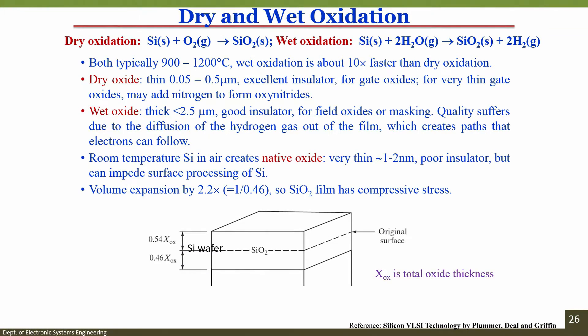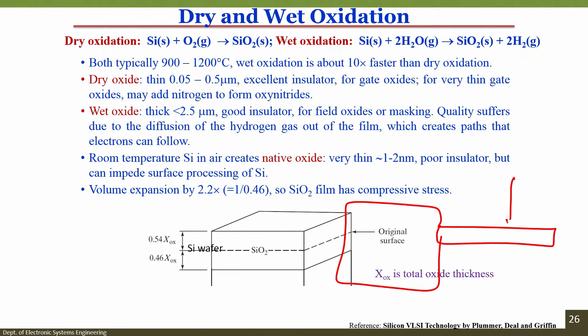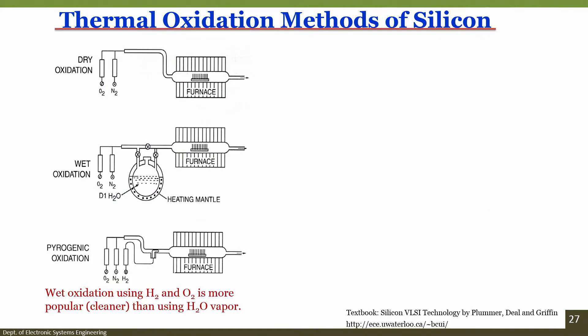Regarding volume expansion: the ratio is 2.2x, equal to 1/0.46. Silicon dioxide creates a compressive stress. When fabricating a device like a piezoresistive cantilever, to compensate this compressive stress you grow or deposit silicon nitride on the back side of the wafer. The cantilever is a silicon wafer, and depositing silicon dioxide on it introduces compressive stress, which is compensated by the silicon nitride on the back side.